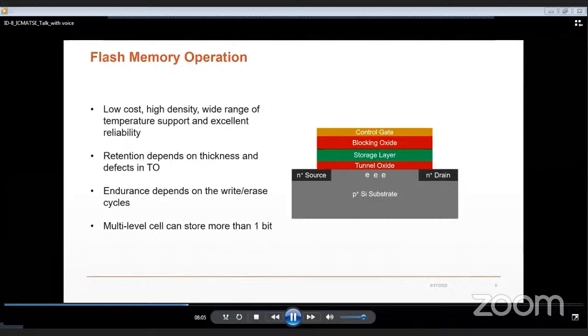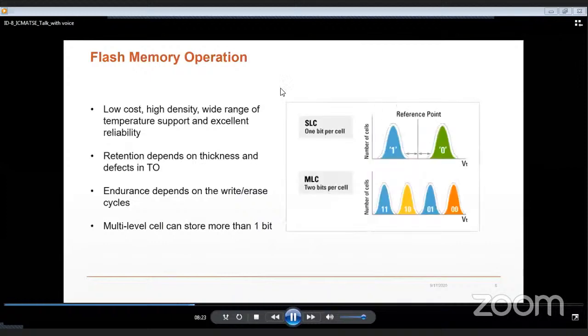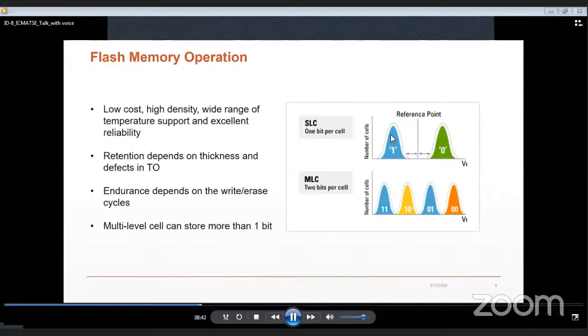In fact, when applying multiple program erase cycles, due to the high electric fields across the tunnel oxide, which can reach up to a few megavolts per centimeter, defects will be introduced in the tunnel oxide, which cause variations in the threshold voltage. Flash memory devices pass data in the form of binary signals. A single level cell stores 2 states, either 0 or 1, while a multi-level cell can store 4 states, for example, and each ranges for 200 millivolts with a data space or margin of 0.2 to 0.4 volts in between each range in order to keep the threshold voltage distributions from overlapping.